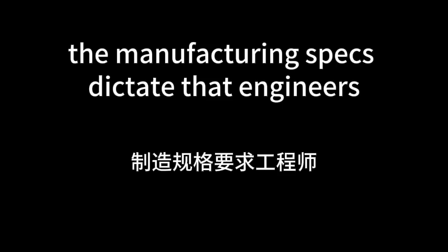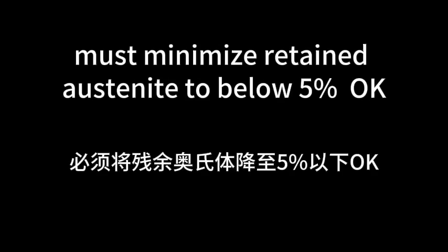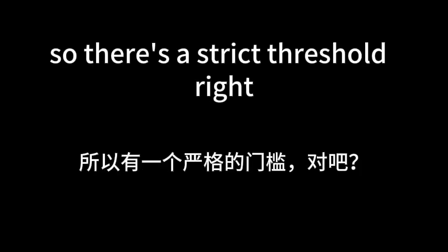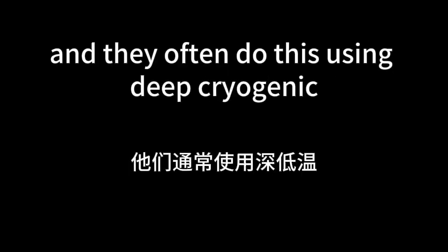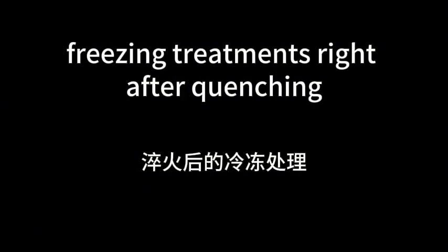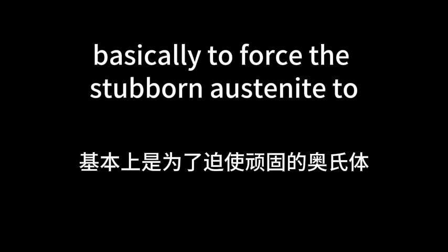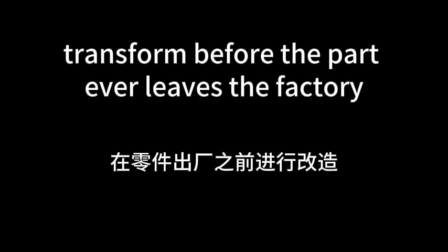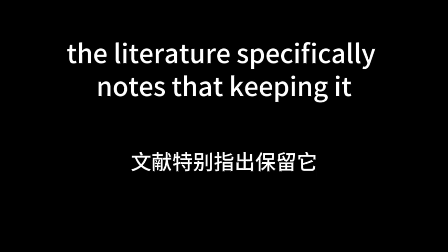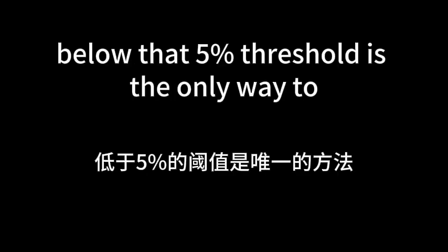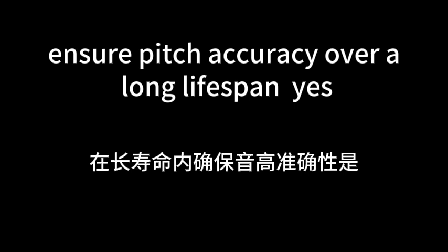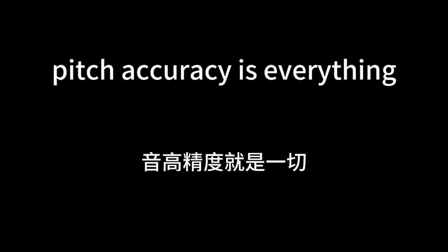The manufacturing specs dictate that engineers must minimize retained austenite to below 5%. Okay, so there's a strict threshold. Right. And they often do this using deep cryogenic freezing treatments right after quenching, basically to force the stubborn austenite to transform before the part ever leaves the factory. The literature specifically notes that keeping it below that 5% threshold is the only way to ensure pitch accuracy over a long lifespan. Yes, pitch accuracy is everything.